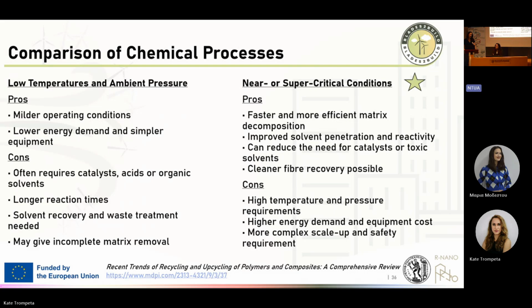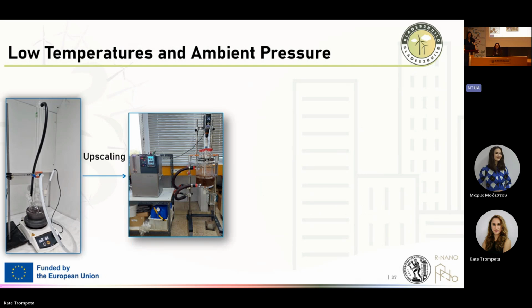But in our case here, in our lab, we have tested both of them. And because of our applications, we consider that supercritical solvolysis is a better option for us since we have cleaner fibers and less time. In the low temperature solvolysis, as you can see here, it was very easy to upscale from 100 milliliters to 10 liter reactors because the kinetics don't change dramatically when you upscale the reaction.